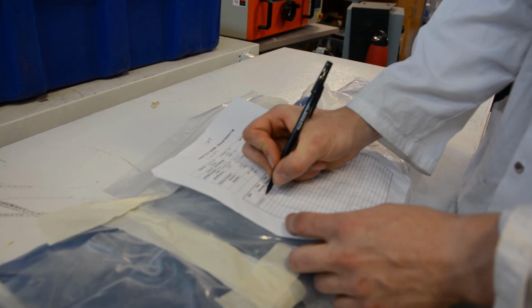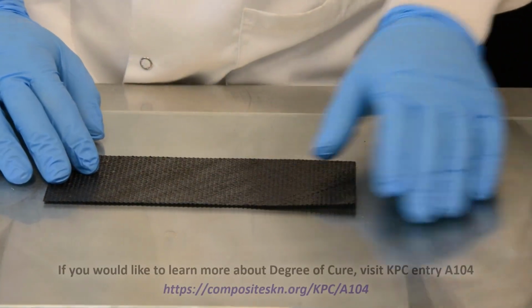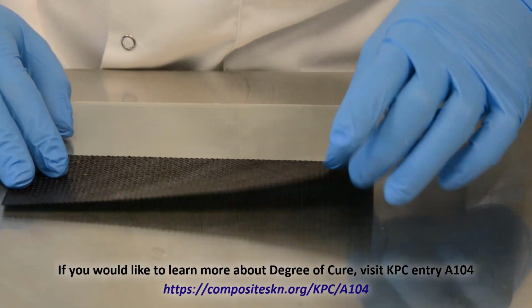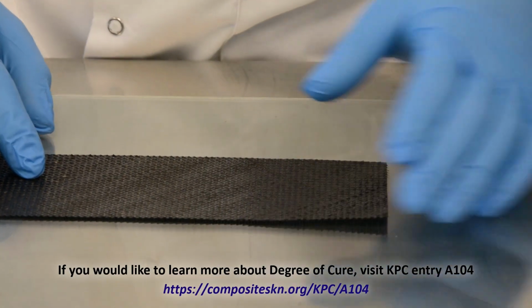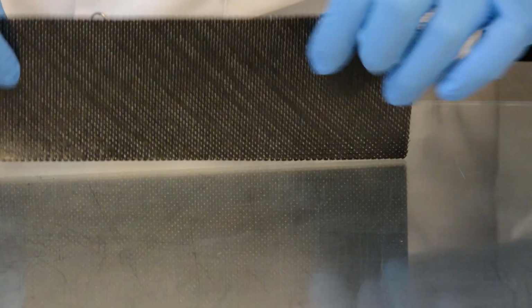The total cumulative amount of time that a roll of material has experienced room temperature is called its out time. Out time is typically tracked and should be minimized as much as possible. When the degree of cure becomes too high, it can be difficult to process into parts. It becomes stiff and less tacky, making it difficult to place into the tool.